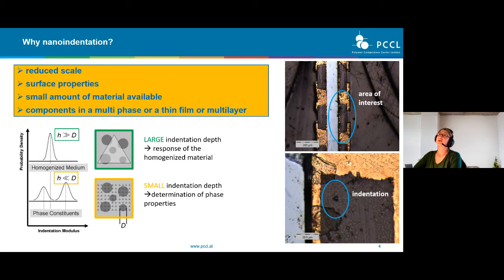Why do we use nanoindentation? We can use nanoindentation because we want to measure on a reduced scale, which you can see here on the right side. There is a small area of interest, and in this small area we can do nanoindentation. We can also measure only surface properties, or we can do nanoindentation if we have only a small amount of material available. Furthermore, we can measure components in a multi-phase, on a thin film, or in a multi-layer. You can see down here in this picture that when we do a large indentation depth, we can get the response of the homogenized material. But if we do shallow indentation, which you can see here in yellow, then we can get the properties of the different phases of a material.